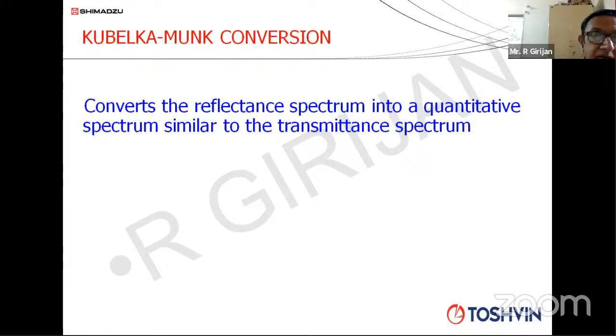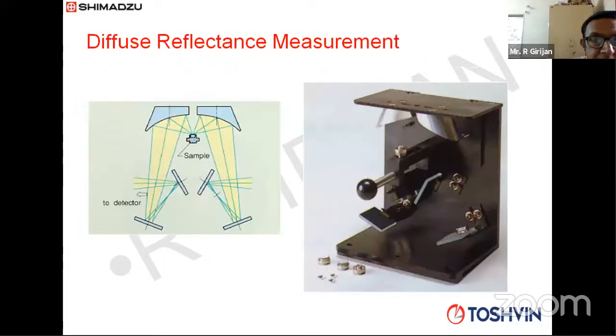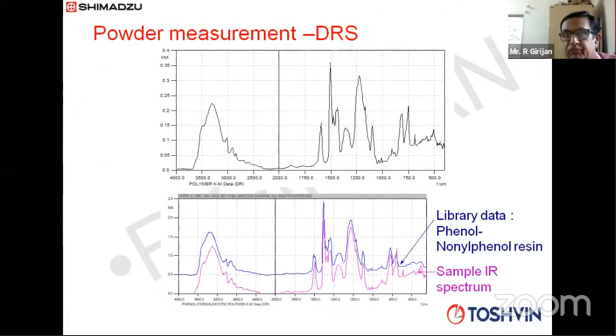So Kubelka-Munk conversion, which is a mathematical conversion, is converting the diffuse reflectance spectrum of the material into a quantitative spectrum, which is very, very similar to the transmission spectrum. So whenever you are using a DRS, diffuse reflectance study, don't forget to apply the Kubelka-Munk conversion after getting the spectrum. It can be done in the software.